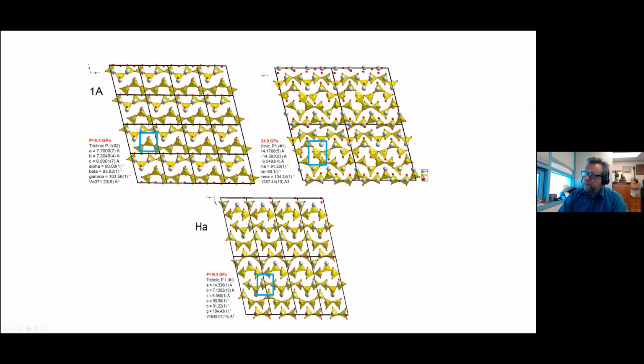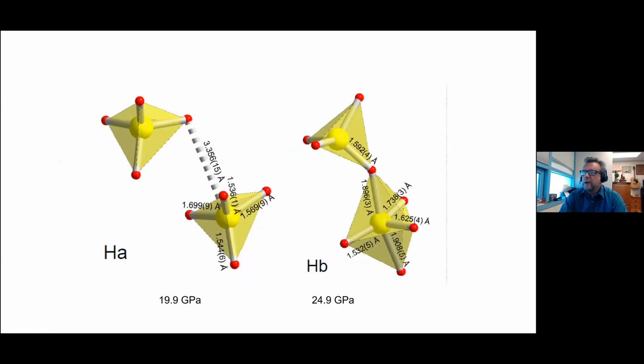So we have coexistence of 4-fold coordinated silicon and 5 coordinated silicon at this pressure of about 25 gigapascals. If you look at the details of the geometry of this site that becomes 5 coordinated, you can see that it's a distorted trigonal bipyramid. There are a couple of different geometries possible for sites with 5 coordinated silicon. We have the bonds that are out of plane, the apical bonds, a little bit longer than the bonds in this central triangular face.